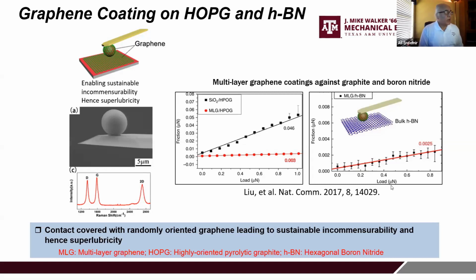But if you have a graphite coating on the microsphere, rubbing against the same kind of graphite surface, the friction almost vanishes. Doing the same experiments against hexagonal boron nitride also showed extremely low friction. So these microspheres favor incommensurability, with only a few direct atom-to-atom registry or commensurate states, giving this favorable incommensurate state of contact and thereby extremely low friction coefficient.